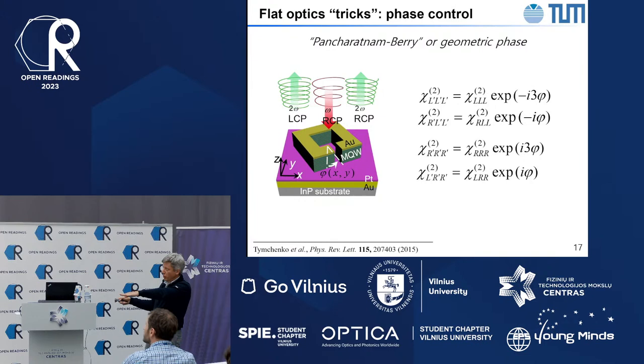Now, if I rotate this antenna, the distribution of the currents in the rotated antenna is going to be exactly the same as the distribution of currents in the original antenna, but just half a cycle or a quarter of a cycle later, because the antenna will have exactly the same orientation with the electric field in the circularly polarized light just a little later. Circularly polarized light keeps rotating, and so the rotation of the antenna really amounts to the phase shift in the antenna response. You can also do it mathematically, but this conceptual thinking is the easiest.